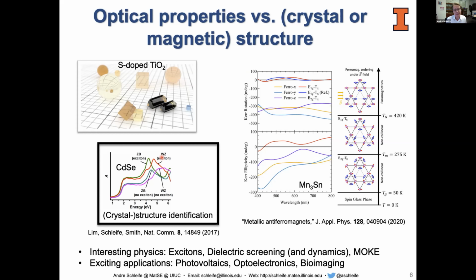In this case, what we show here in this figure is bulk simulations for the material. We also performed the simulations for nanocrystals, and we found indeed that while the absorption onset does not tell these two crystal structures apart, let's say for instance comparing the red and the green curve here, at higher energies there are characteristic peaks that correlate with specific crystal structure.